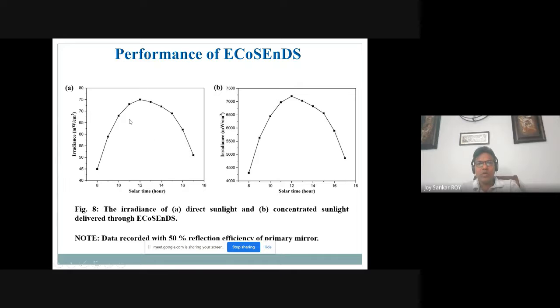But you see from our system, you are getting almost more than 7,000 milliwatt per centimeter square. So it is close to 1,000 times higher than what you normally get. But still, this is our first experience. First we set up this instrument, we didn't know what would happen. Actually we did not coat the primary mirror fully, 100% coating. We put some aluminum coating and then silicon coating over the primary mirror to reflect the sunlight properly. We coated only 50%, so if we coat 100%, the energy will be much higher.